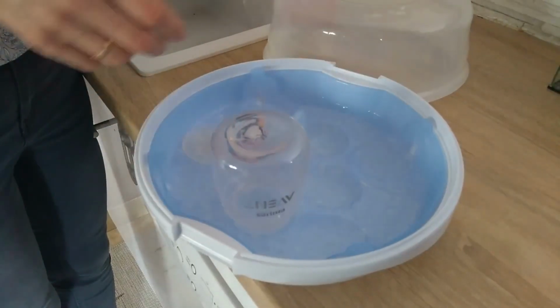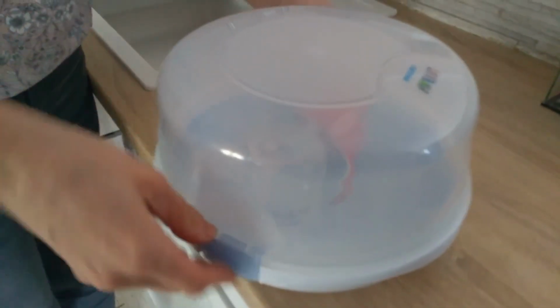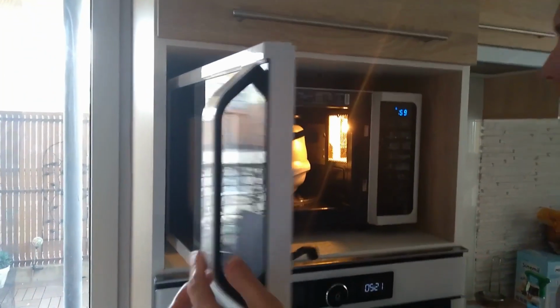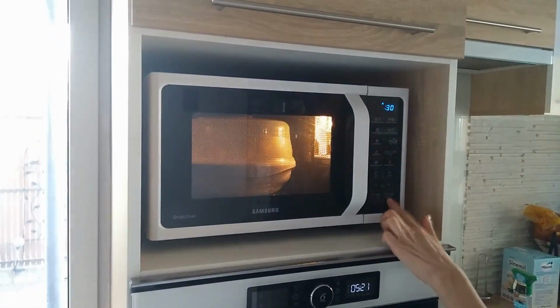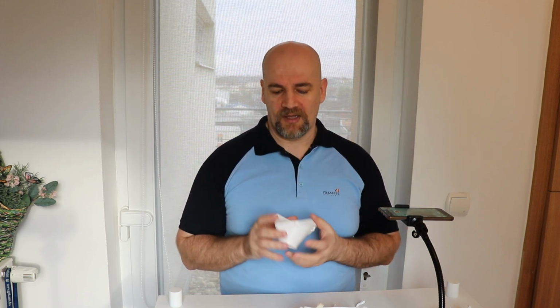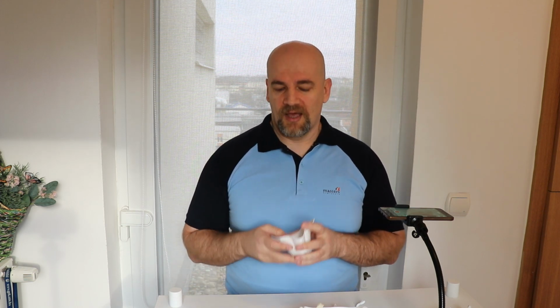The third solution is annealing of the PLA, because our youngest daughter is 2 years old, and we are sterilizing her dishes and bottle in the microwave. But the problem is that PLA, for example, cannot handle this kind of temperature. But with annealing of the PLA, we raise the temperature resistance so it can be sterilized. The only problem is that when you put it in the oven for annealing, it will definitely shrink and deform. So you 3D print a mask, you have perfect sealing, and you put it in the oven for annealing, and then it will shrink, it will deform, and you don't have perfect fitting anymore. So that's one big problem with annealing.